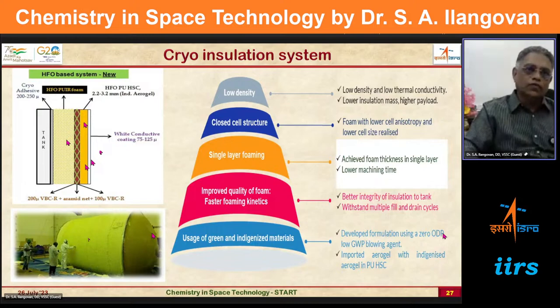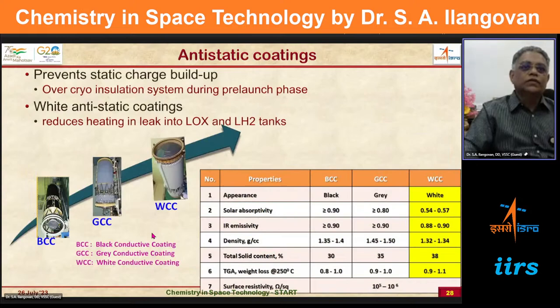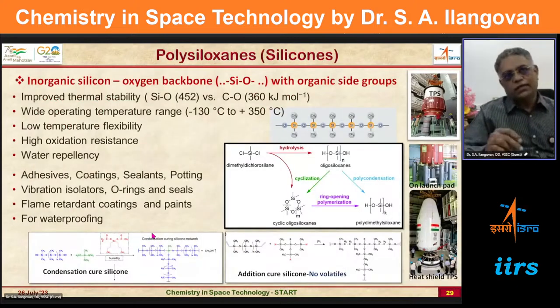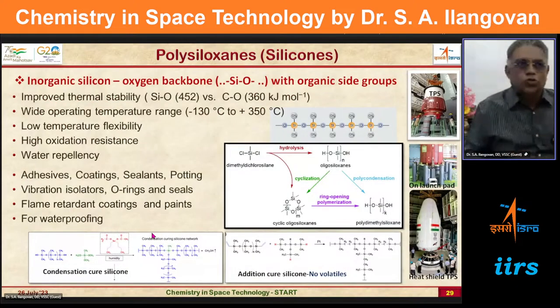So this is our spin-off for making all the foams. In every home we have the polyurethane foam, the PU foam. It is nothing but this material. This is how the spin-off has come from space development. And this is yet another development where we have made a conductive coating. One was the black conductive coating we were using. Now it was gray. Now we have made it as an all white conductive coating. So the emissivity, solar absorption, all the things we were able to meet. So it is a chemistry, and that has brought about space technology achievements and desirability, not only for us, for the spacefaring nations also.